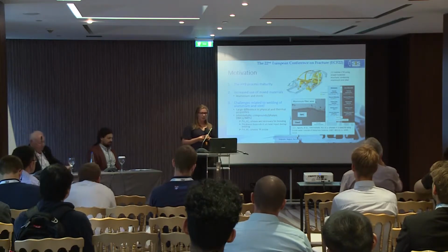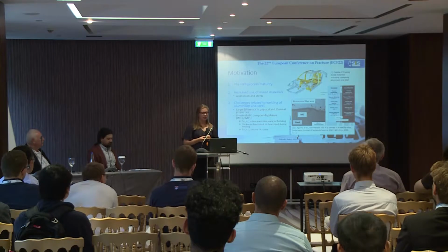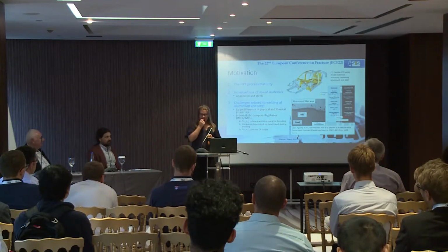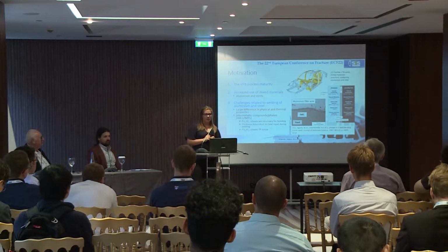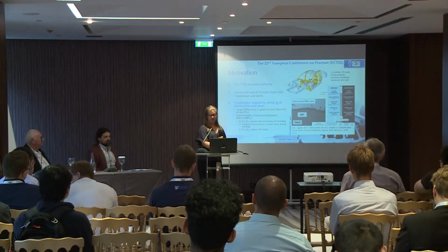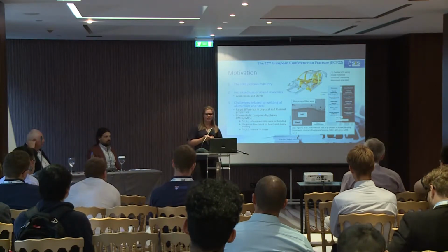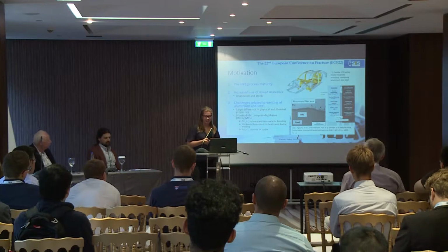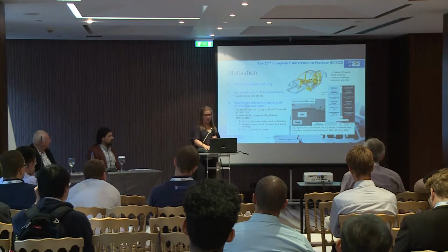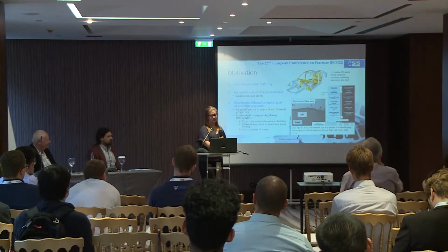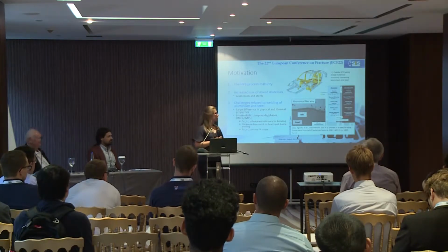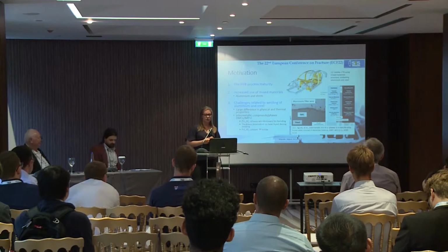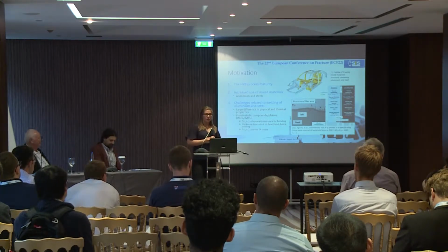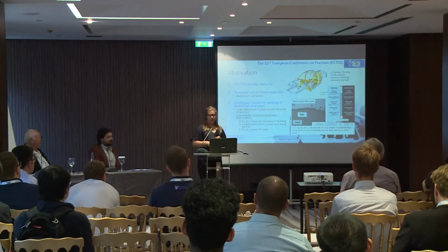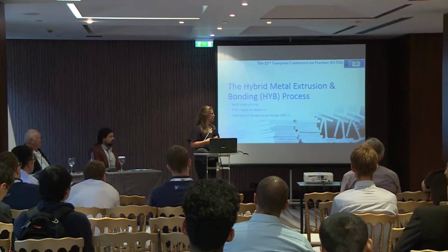These phases, aluminum and steel, are necessary to achieve bonding, but the high thermal input associated with conventional welding techniques leads to an excessive formation of these phases, which results in a brittle bond. And thus they determine the bond strength or the joint strength. So what we wanted to see was if the HYB process also could be used for joining of aluminum and steel. But before that, I'm going to explain to you how the HYB process works.